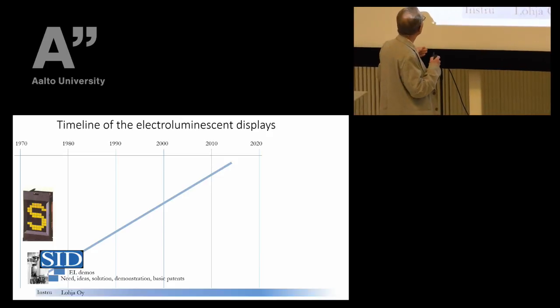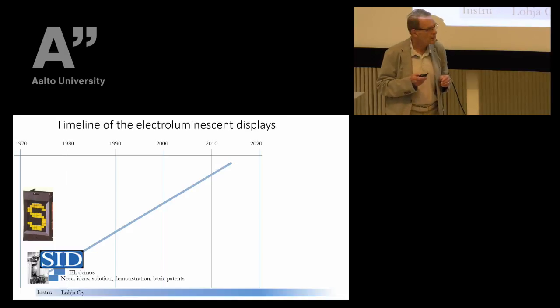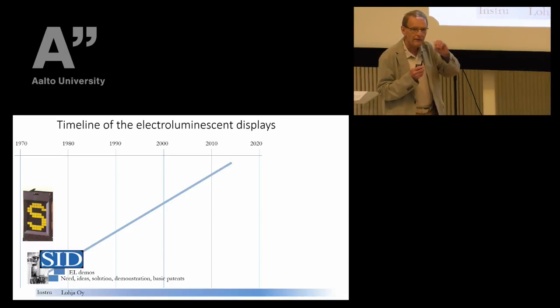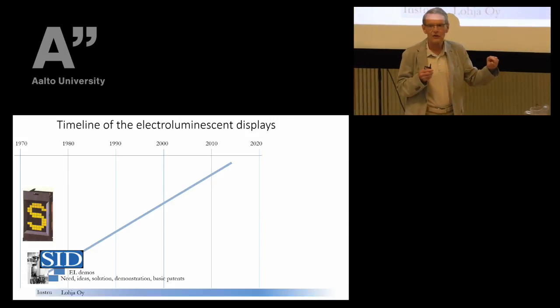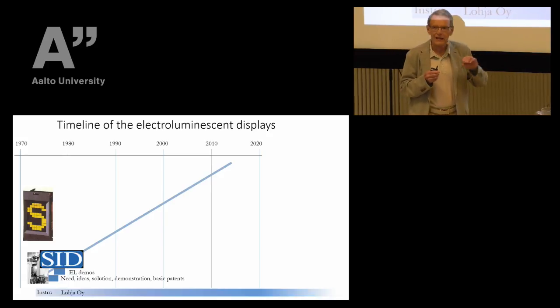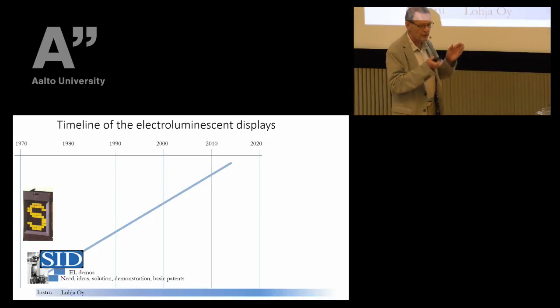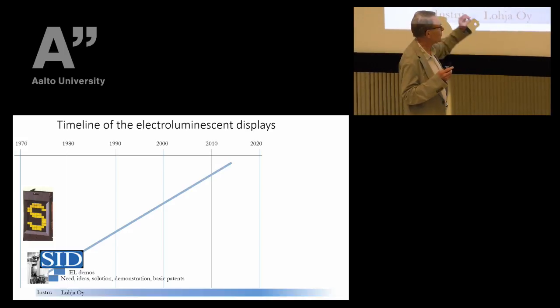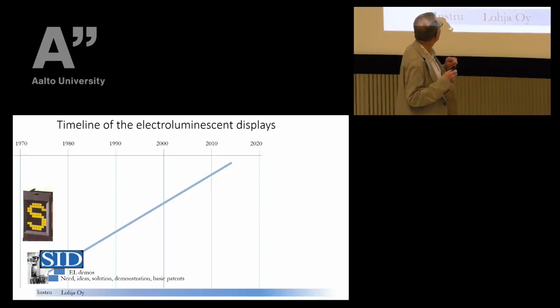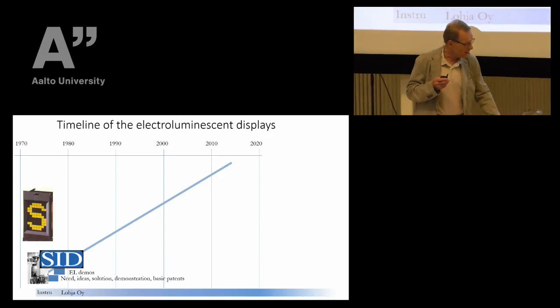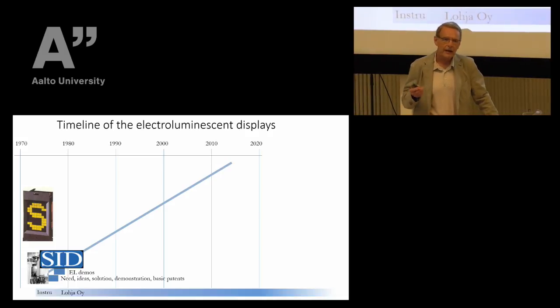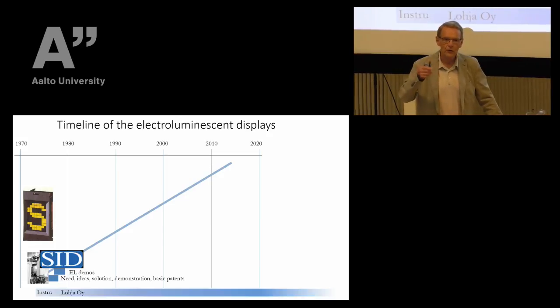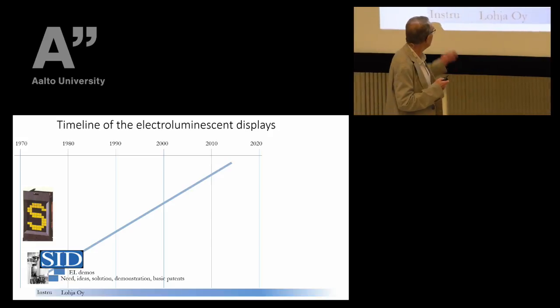So finally we got the EL panel fabricated, and it turned out that the ALE films really had much better properties than any demonstrated at the time. The problem is that we have a 200 volt voltage across a one micron film thickness, which means we need really excellent dielectric strength. And it turned out that with ALE, the dielectric strength of the materials was better by a factor of 2, 3, or even up to 10 in some particular cases, so that it really had a big influence. That was a huge success.